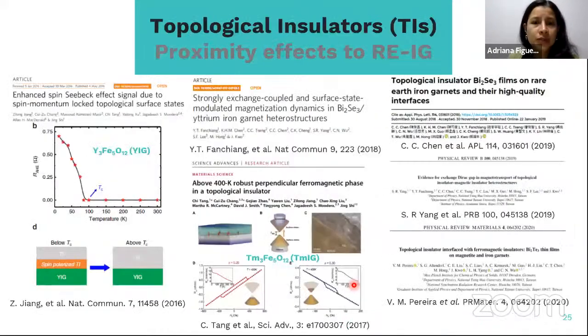All right, and then we do this not only for the europium sulfide. Our next study was to use other kinds of magnetic insulators, those that have, for example, higher Curie temperatures. For example, YIG, which is yttrium iron garnet, or thulium iron garnet. So these rare-earth iron garnets have also been studied in interfaces in heterostructures with topological insulators in search of these proximity effects. And in magnetotransport measurements, it has been reported that there are some spin polarized features at the interfaces of those magnetic insulators with the TI.